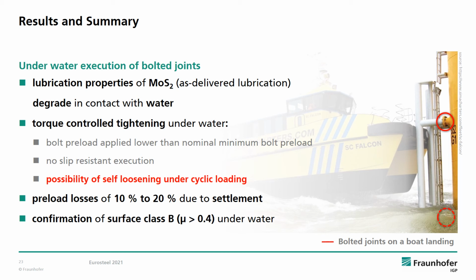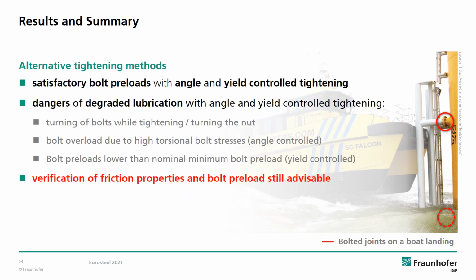However, slip behavior of the connections tested underwater looked different from the connections tested under regular conditions. While specimen tested under regular conditions continuously slipped until they came to a hold slowly, specimen tested underwater slipped continuously until they lost hold abruptly. Bolts tightened with alternative tightening methods compared to torque-controlled tightening reached satisfactory levels of bolt preload, meaning above design preload level, even with degraded lubrication.